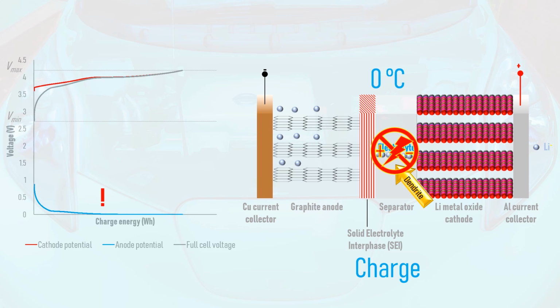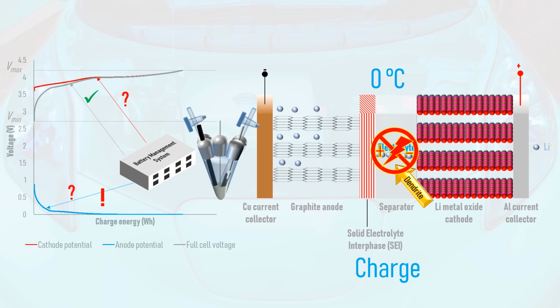Even when lithium plating is taking place, the full cell voltage can appear to be fine as long as the cathode doesn't go above the maximum potential of the full cell. As alluded to previously, the EV's battery management system can read the full cell voltage fine, but has no way of determining the cathode or anode potentials individually, and so is oblivious to any lithium plating taking place. The BMS could technically monitor the potential of each electrode in isolation if the cell had a third reference electrode made of lithium, but this is only done in the lab.